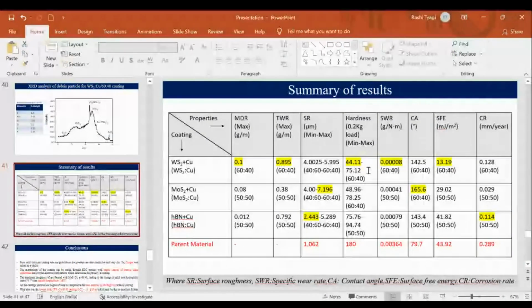Also the hardness is lowest for WS2 plus copper coating, and surface energy is lower for WS2 copper coating. But the contact angle we can see is higher for the MoS2 plus copper coating, as it has the highest surface roughness, because the highest surface roughness is responsible for a high contact angle. And for corrosion resistance, you can see it is highest for HBN copper coating.